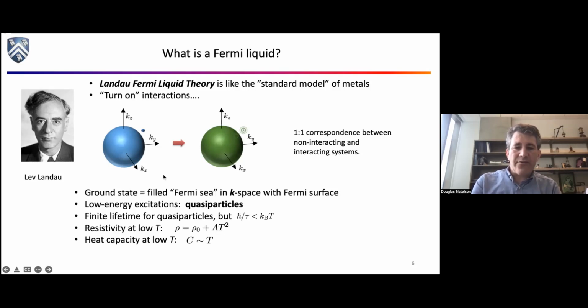Well, it turns out that the ground state is still a bunch of filled states in k-space. There's still a boundary, so a Fermi surface. The low energy excitations are now called quasi-particles. They're particle-like, but they don't live forever, okay? They've got a lifetime, tau, but that lifetime is such that the energy uncertainty, like h bar over tau, that's kind of how fuzzed out in energy the particles are because they only live a finite time. That energy uncertainty is always smaller than kT, the thermal energy scale. What that means is that the quasi-particles out here are always energetically distinct from the Fermi surface.